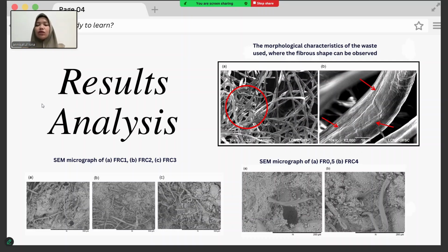However, as fiber content increased to FRC1 and FRC2, slight agglomeration and voids start to appear. Then in FRC4 shows heavy clustering and visible gaps, weakening the overall structure. From this observation, it can be concluded that 0.5 weight percent fiber provides the best microstructural reinforcement, while excess fiber addition causes poor dispersion and lower mechanical performance. Next.